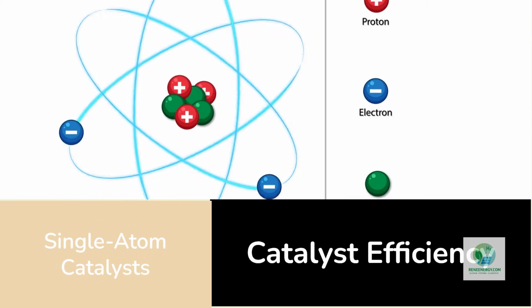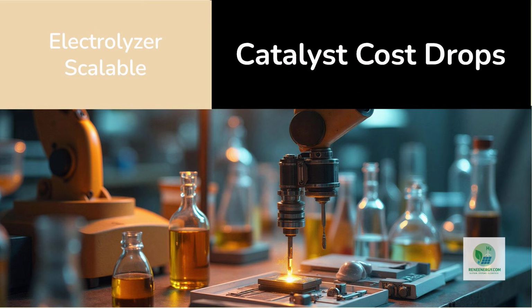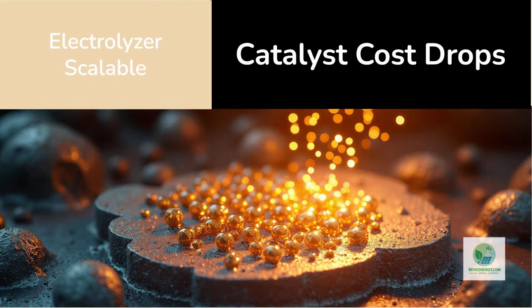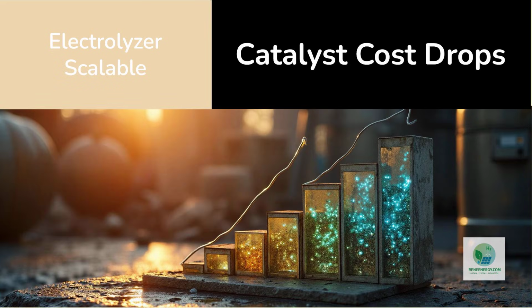In published results, loadings dropped from 2 milligrams per square centimeter to as low as 0.02 milligrams. That is a 100x reduction. These catalysts are stable, resistant to dissolution, and cheaper by orders of magnitude. What's more, this is not limited to noble metals. Teams at the Korea Institute of Science and Technology have created cobalt-based single-atom catalysts that match or exceed the oxygen evolution performance of iridium. Meanwhile, research from Lawrence Berkeley National Laboratory has demonstrated atomic layer deposition techniques that precisely place catalyst atoms in monolayers, minimizing material usage while boosting stability.